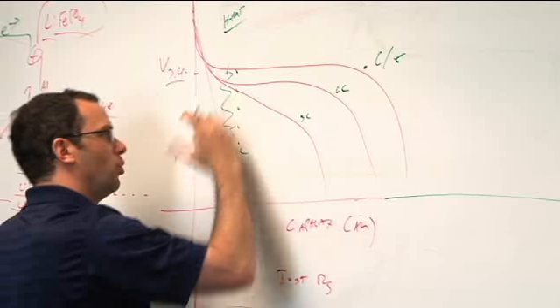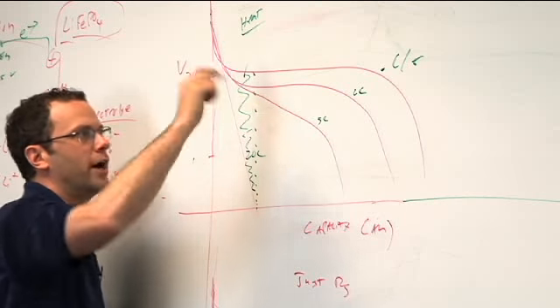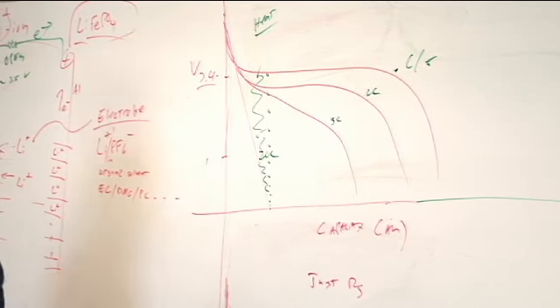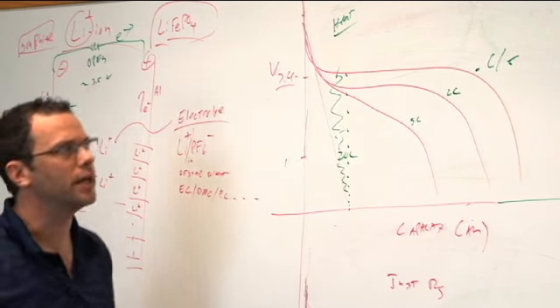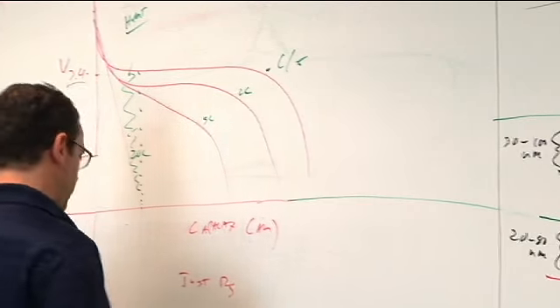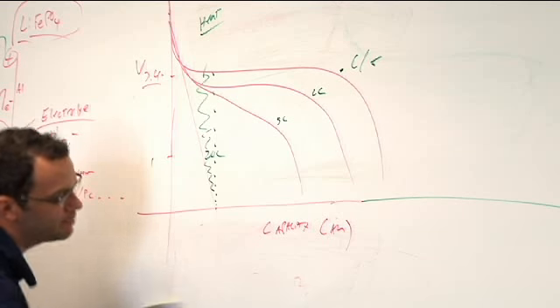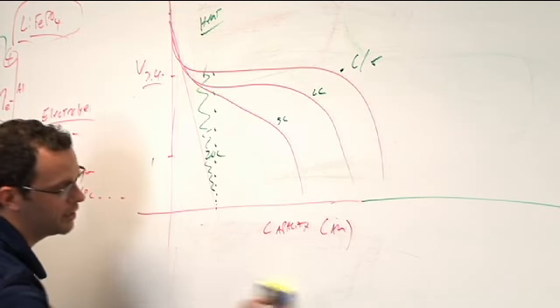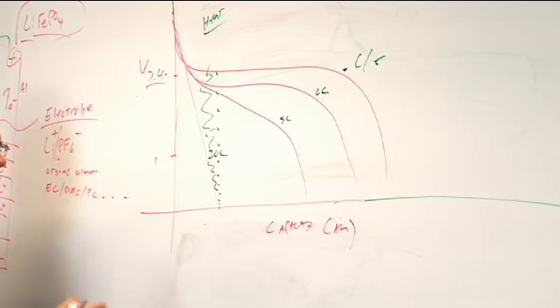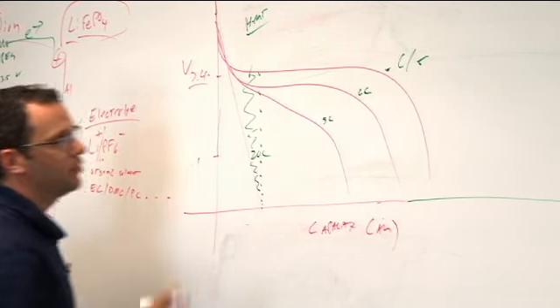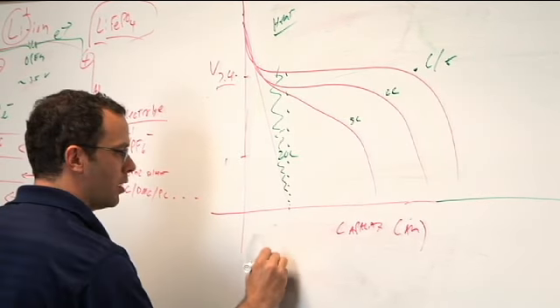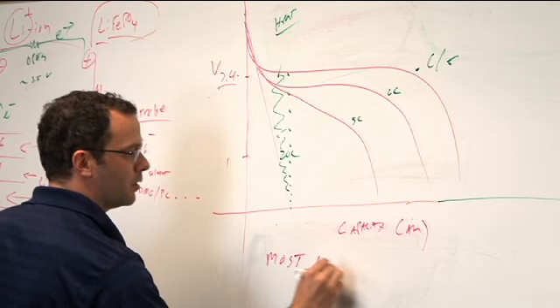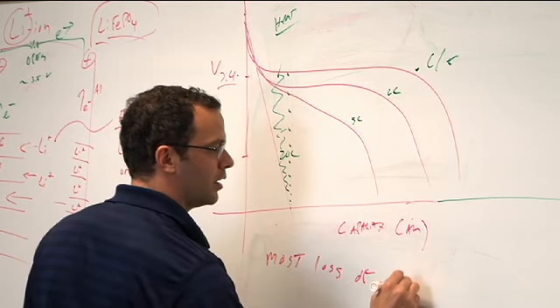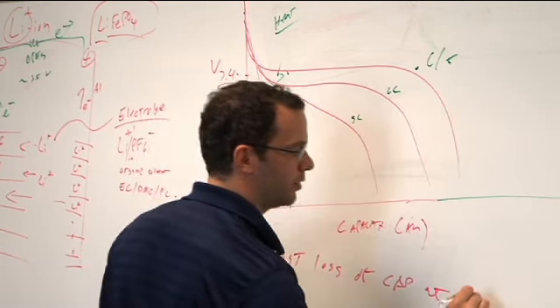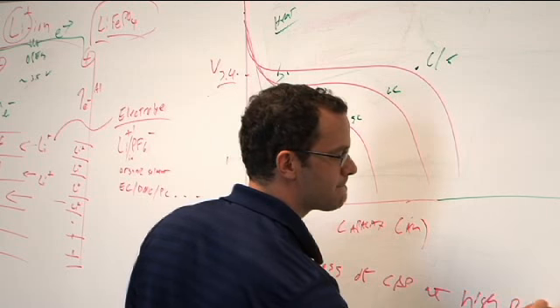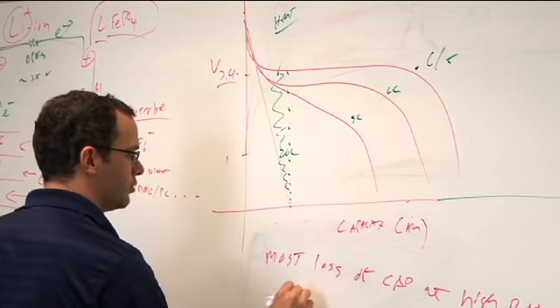This significant voltage drop and this significant change in the profile of the curve is what we call concentration polarization, okay? And this is really a key part of what we need to figure out and understand about these batteries. And I would say the majority of the loss, most loss of capacity at high rates, equals concentration polarization.